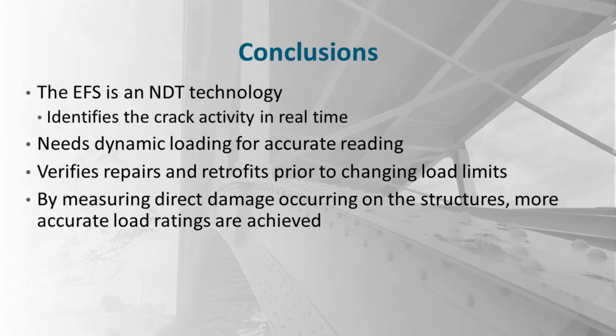So the conclusions after the study: the EFS is an NDT technology that can identify cracks and the activity of the crack in real time, that it needs dynamic loading for an accurate reading, and it can verify repairs and retrofits prior to changing the load limits. And by measuring the direct damage occurring to the structures, more accurate load ratings can be achieved.